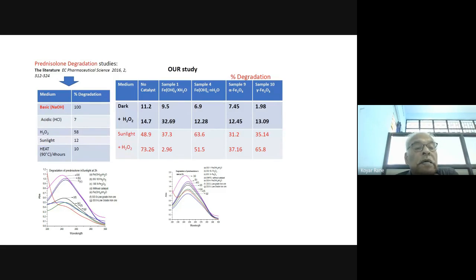We have also used pharmaceutical products like prednisolone, which is widely used, and we do find that catalyst can degrade the prednisolone, whereas the prednisolone degradation has been studied in the literature. You can see that it requires alkali to degrade 100%. So we cannot put alkali in the water to remove such a pharmaceutical product. Acid cannot degrade the prednisolone, whereas H2O2 can degrade around 60% or so. Simple sunlight cannot degrade; almost 12% degradation takes place. Heating also will not do the job of degrading.